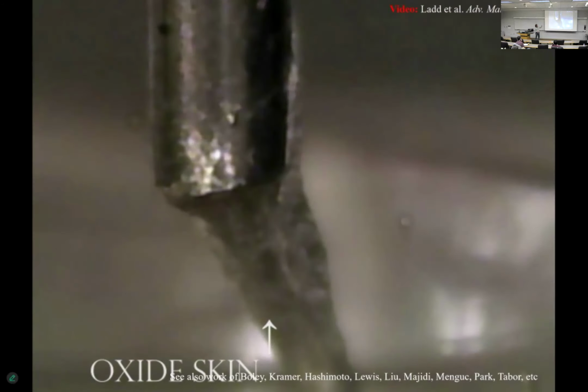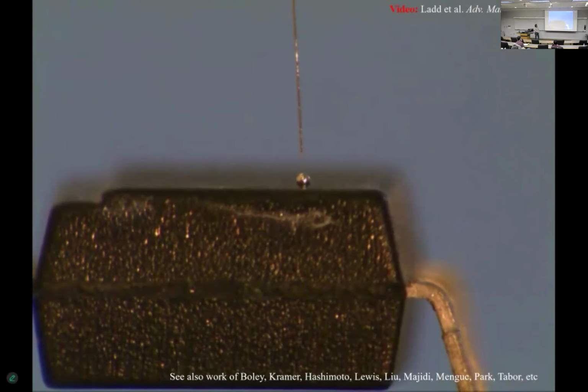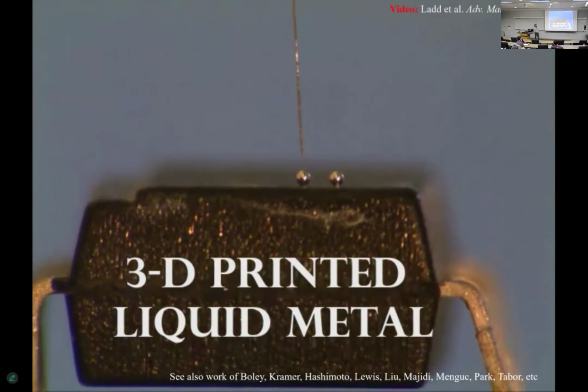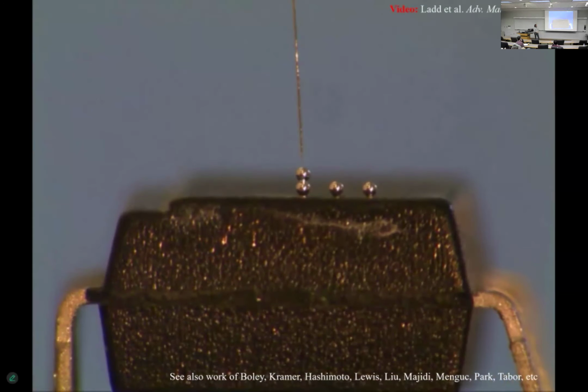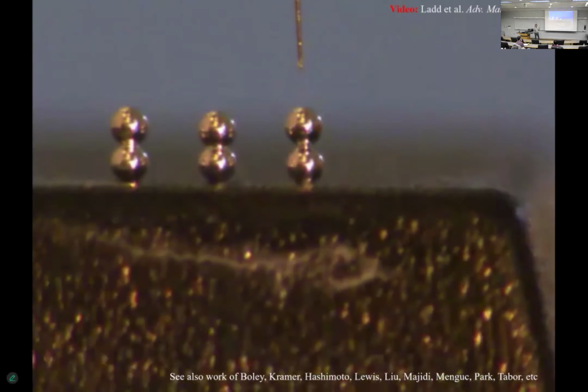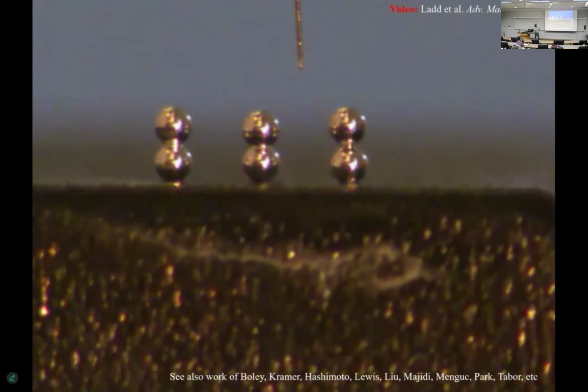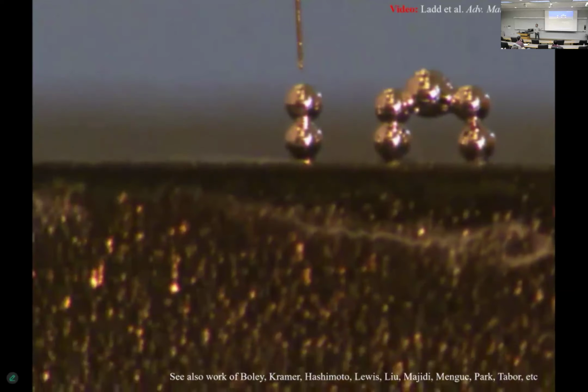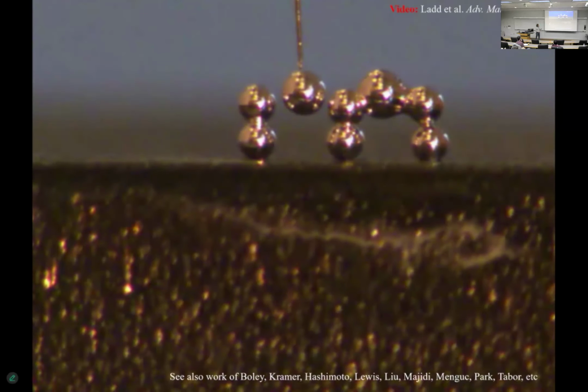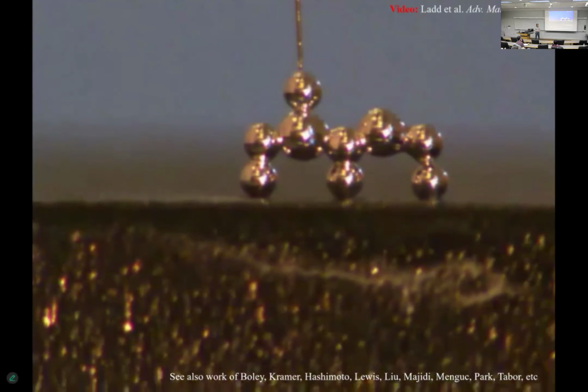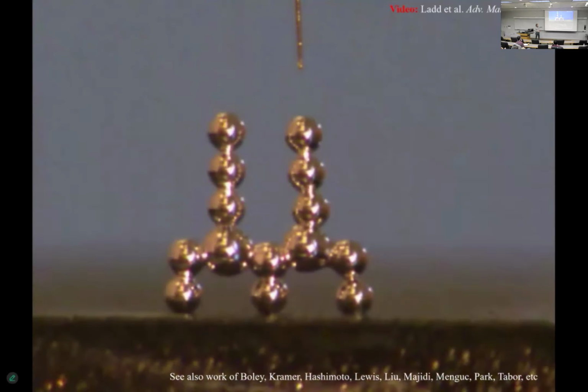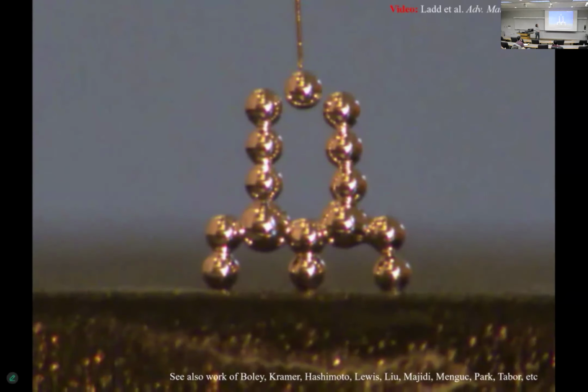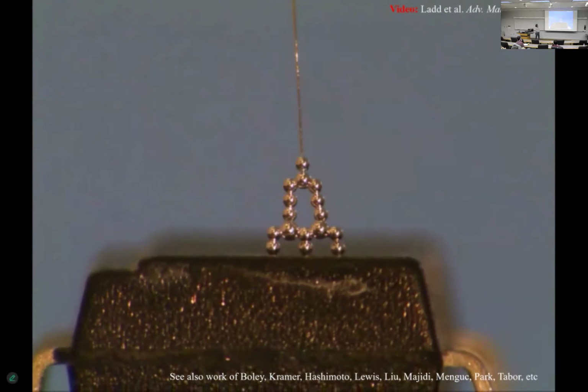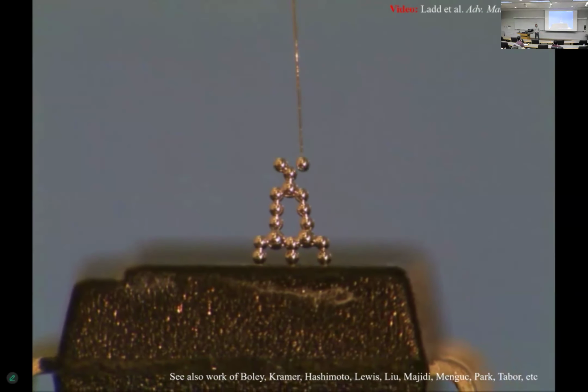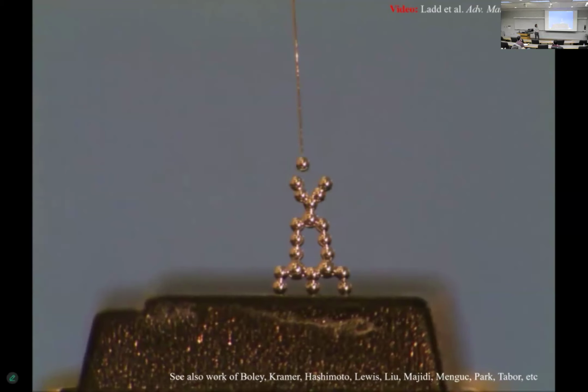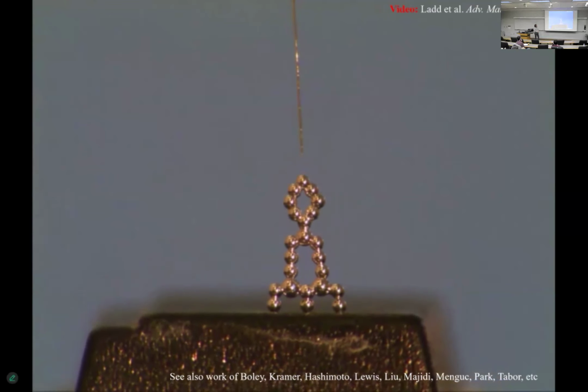So here we're sucking the liquid metal back in. You can see the oxide wrinkle. And this oxide forms essentially instantly, very, very fast. And so as a consequence of this, remember, 3 nanometer thick skin that forms on the surface, we can take this liquid that's in many ways like water and start to make 3-dimensional shapes out of it. So here we're just taking droplets and stacking them. And at the time, this was the first example of printing metals at room temperature in really a very simple way. So here we stack droplets.